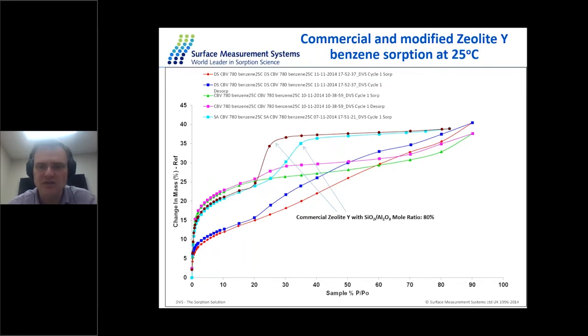let's say like benzene, which is not very common these days in the labs, but we can replace it with toluene. So here we look at the zeolite Y, and we compare the modified zeolite Y with a commercial zeolite Y, and we look at the adsorption desorption at 25 degrees. So what you see here, in this turquoise line, we can see type 4, a lot of type 4 isotherms. So the adsorption with turquoise, desorption in brown.